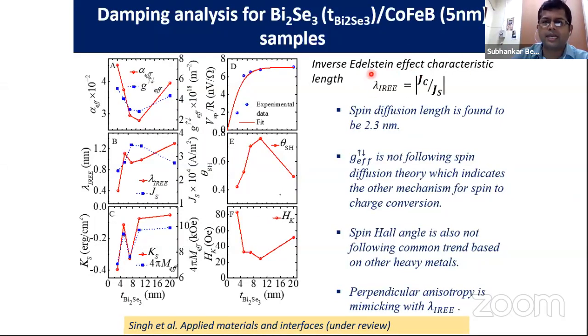And that surface effect is then the Edelstein effect, and this efficiency, spin to charge conversion efficiency, SCCE, you define as lambda inverse Rashba-Edelstein effect. That is basically the Jc by Js in this case, and you can calculate it. And the G effective, the effective spin mixing conductance, which is another important parameter, is actually behaving like that, so it is not following the spin diffusion theory. But one important message of this manuscript, which is under review, is the surface anisotropy. If you plot as a function of thickness the 4 pi M effective, it actually behaves very similarly. So that shows that the inverse Rashba-Edelstein effect is more prominent in these samples. So this basically comes from these surface Dirac states.